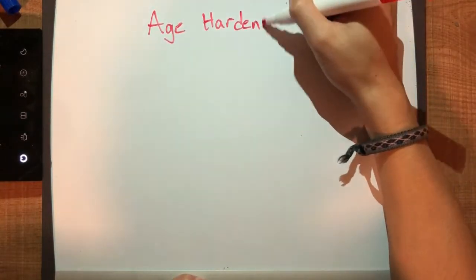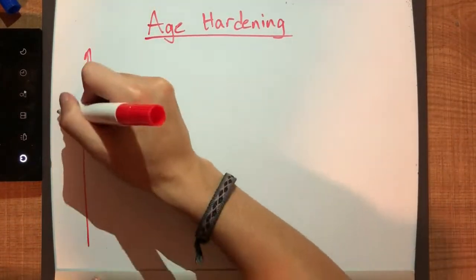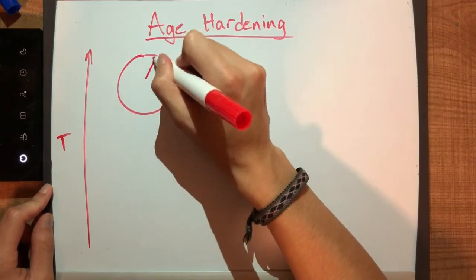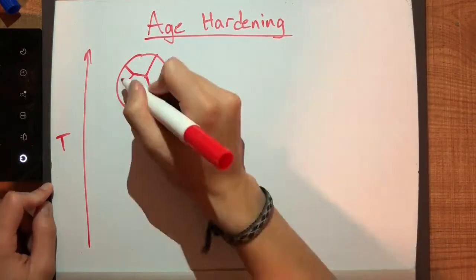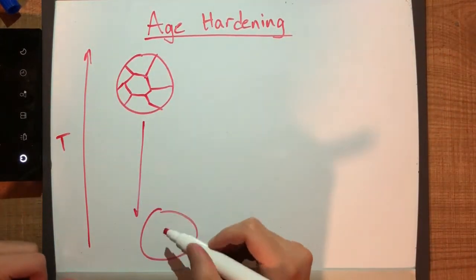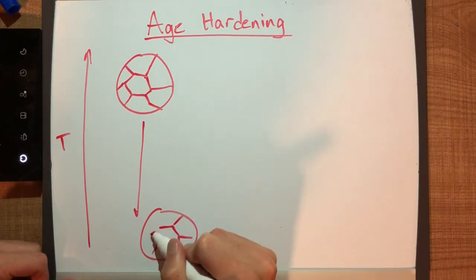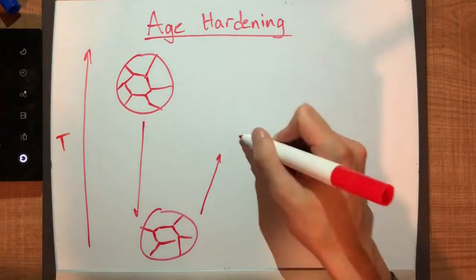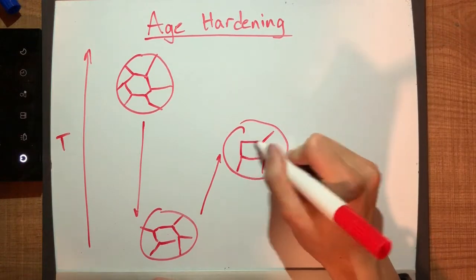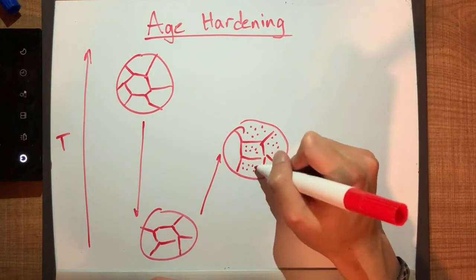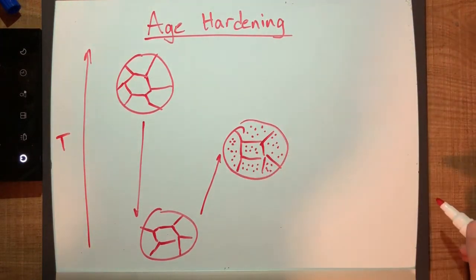The steps previously mentioned harden the material because of their effects on the microstructure development. As the temperature is raised above the solvus temperature, the alloy becomes a solid solution, and once quenched, becomes a supersaturated solid solution. Then, when raised to a mild temperature, precipitates begin to form, which are responsible for the hardening effect.